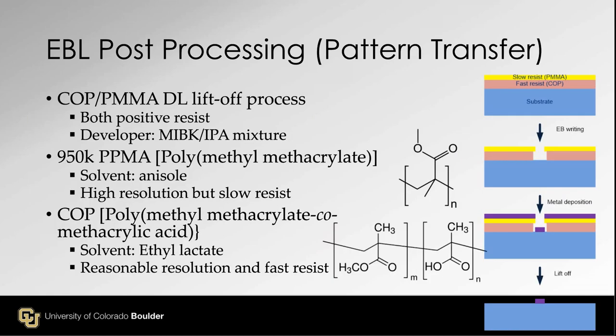Okay, I said post-processing pattern transfer is required, so I want to show you the typical process here. For the liftoff process, a copolymer and PMMA double layer recipe is often used for positive resist. The developer is a mixture of MIBK, methyl isobutyl ketone, and isopropanol. Then you start with a substrate and the double layers. After e-beam writing and development, the exposed area is removed. Then after that, you put a metal thin film on by evaporation or sputter coating, or any other thin film deposition method, and you remove the resist. You have a tiny area of metal.